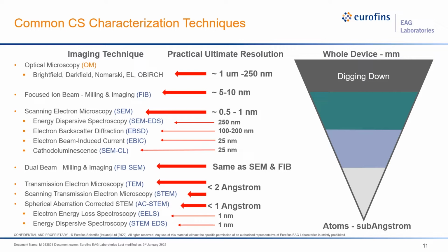And then we can extend that down into scanning microscopy techniques: SEM, SEM-EDS if we want some elemental analysis, EBIC, cathodoluminescence. And then that takes us further. The spatial resolutions of SEM are down on the order of 1 nanometer now. So that gives us very high resolution in most cases, but it doesn't really give us much information about the crystallography in the sample, which oftentimes the defects that are causing the degradation are crystalline in nature.